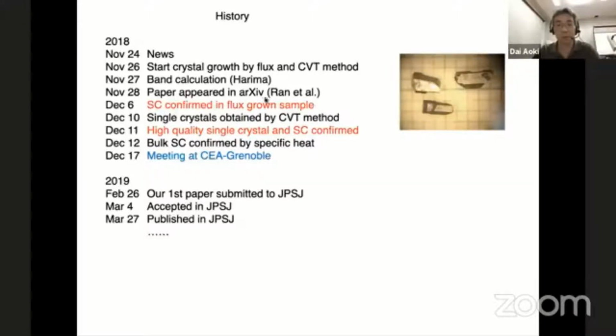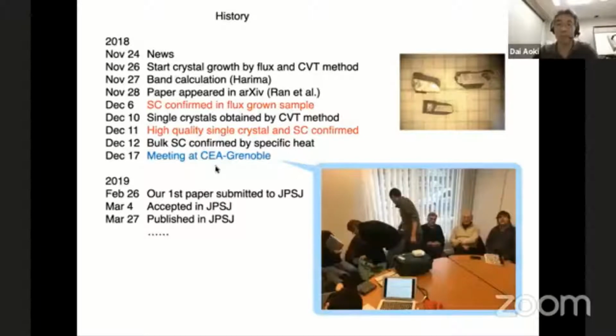We really confirmed the superconductivity. This is grown by the flux method. Then we got a higher quality single crystal grown by the chemical vapor transport method, and we confirmed the bulk superconductivity by specific heat and so on. Then I went to France immediately, and we had an emergency meeting. Here you can see a photograph of the meeting. This is Georg Knebel, this is Jacques Flouquet, and this is Mineev. And this is Jean-Pascal Brison, and this is Gabriel. My target was to make a strong collaboration between France and Japan, and to fight against the American team.